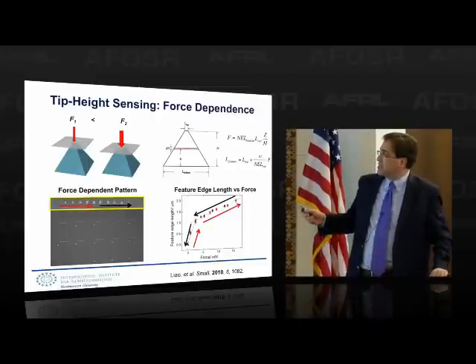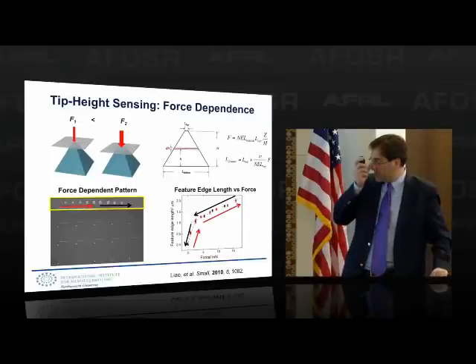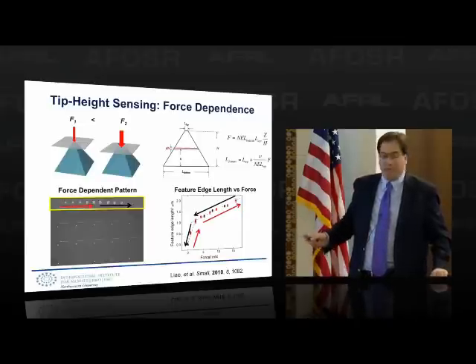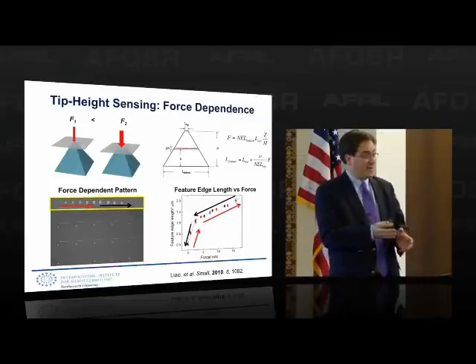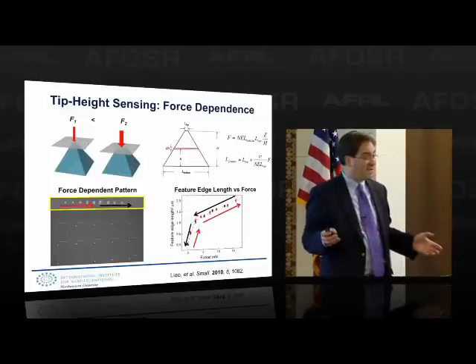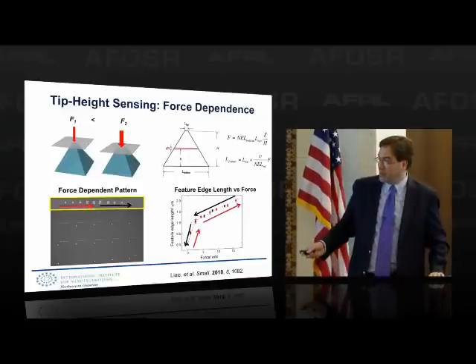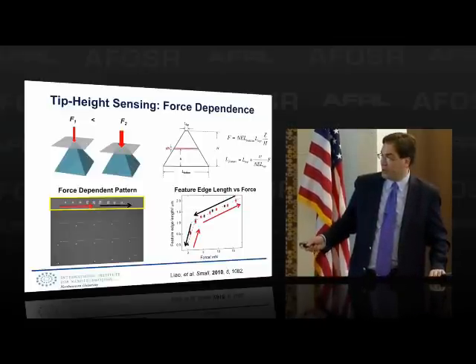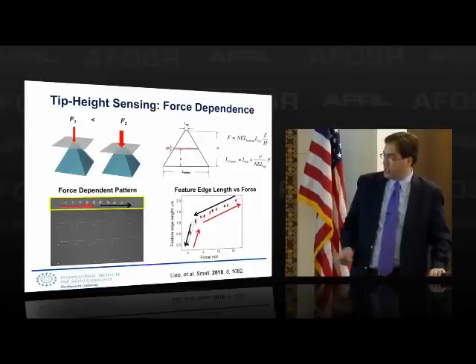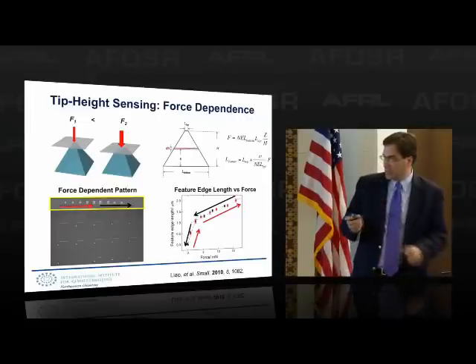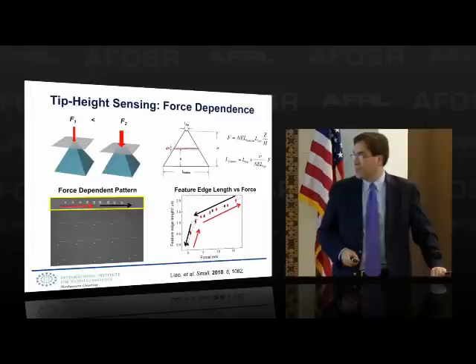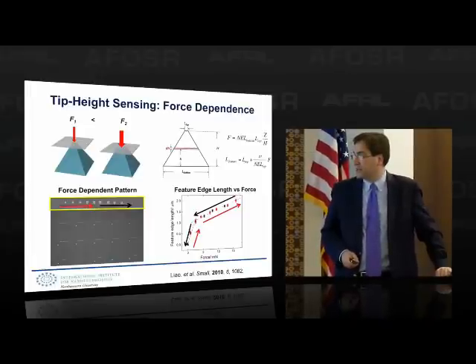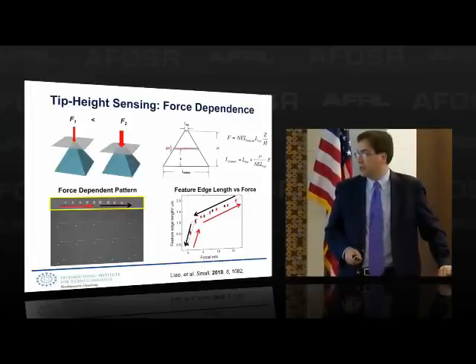As I said, it's just from simple geometric arguments, it's very modelable. You have to take into account, though, that the polymer has a compression modulus that depends upon contact force. And so that's important in terms of modeling this, because you can't model it all on this one. You have to then throw into your model a change here when you get to a few millinewtons in terms of contact force. And that takes into account the restructuring of the polymer chains within the elastomer as you're applying a larger and larger load.